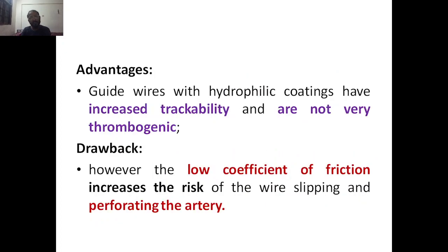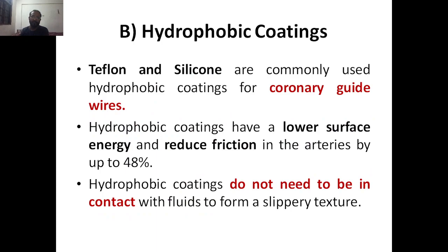Advantages: guide wires with hydrophilic coatings have increased trackability and are not very thrombogenic in nature. That means they will have reduced thrombogenicity. They will not cause any clotting effects. Those are the advantages. Whereas the drawback is that the low coefficient of friction increases the risk of the wire slipping and perforating the arteries. If there is too much hydrophilicity, it can cause slipperiness, and because of the slipperiness the inside wall can rupture.